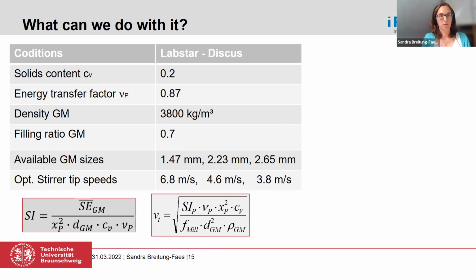The smallest one was around 1.5 millimeter, and the biggest one was around 2.65 millimeter, and one in between. And if you now rearrange at least your equation for the stress intensity to the stirrer tip speed, because it's the last parameter we haven't chosen, we can calculate at least optimum values for these 3 grinding media types, which were for the smallest one around 7 meters per second, then 4.6 for the medium one, and 3.8 meters per second for the biggest ones.